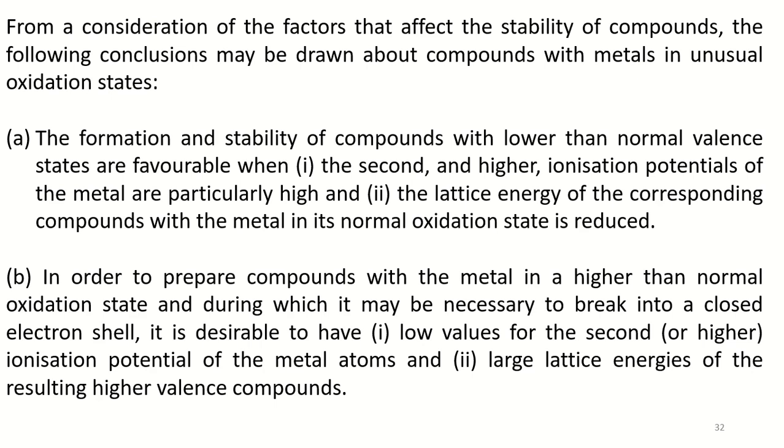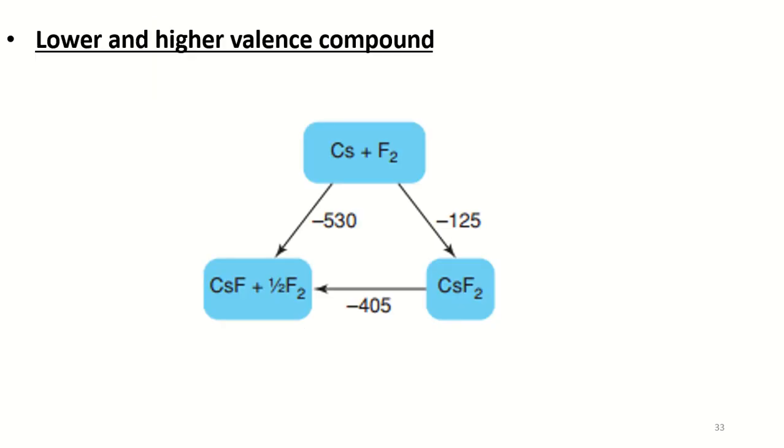Thus, all cesium dihalides apart from cesium difluoride have positive delta heat of formation values and would be unstable. Cesium difluoride CsF2 is stable in principle with its large negative delta heat of formation value, but has not been prepared because its decomposition to cesium fluoride has a large negative delta H.